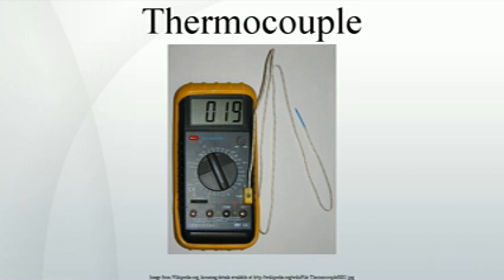Type K. Type K, chromel, alumel, is the most common general-purpose thermocouple with a sensitivity of approximately 41 µV/°C, chromel positive relative to alumel when the junction temperature is higher than the reference temperature. It is inexpensive, and a wide variety of probes are available in its −200 °C to +1350 °C / −330 °F to +2460 °F range. Type K was specified at a time when metallurgy was less advanced than it is today, and consequently characteristics may vary considerably between samples. One of the constituent metals, nickel, is magnetic.